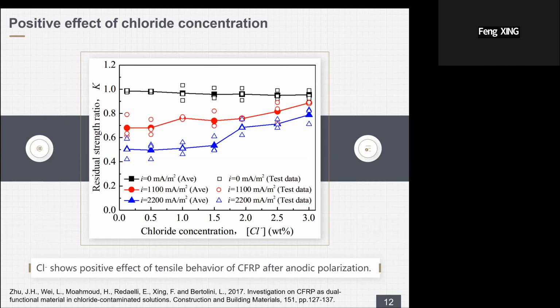It is very interesting, as you can see from the results. The tensile strength of CFRP after polarization increases with the chloride concentration, no matter which current density is used. When 3% chloride was used, the residual tensile strength is around 90%. Therefore, it indicates that chloride has a positive effect on the tensile behavior of CFRP after anodic polarization.